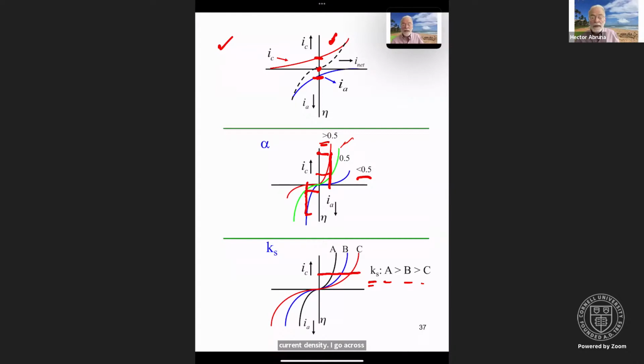To achieve the same rate, which we're controlling by the current density, in the case of A, I apply this much overpotential. In the case of B, this much overpotential. And in the case of C, this much overpotential. And so clearly, to achieve the same rate, I have to expend a much higher overpotential in C than in B than in A, because Ks for A is bigger than B bigger than C. And the same holds here in the oxidative processes.